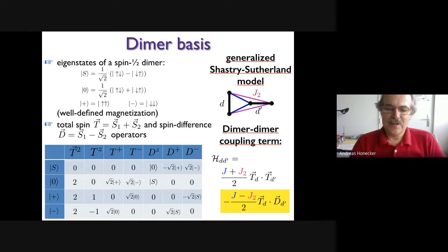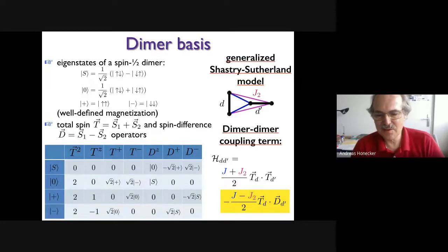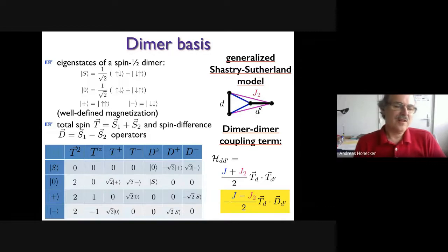So the first line would be fine. There's no negative sign in the first line. The second line might give you a negative sign, as you might see from the matrix elements of the D operator in that dimer basis. There are minus signs or plus signs, so they're different signs. So there might be a sign problem with these signs. But instead of thinking very long about it, it's better to try it out.